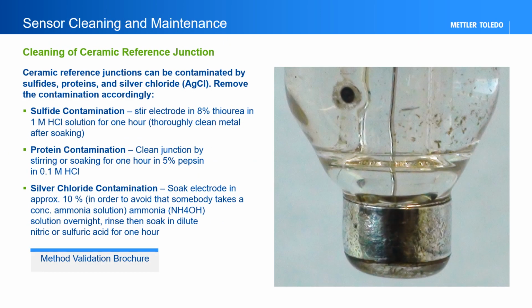A ceramic reference junction can be contaminated over time with sulfides, proteins, or silver chloride precipitate. This contamination can block the flow of the reference electrolyte and must be removed. Pictured here is a silver ring electrode with a ceramic reference junction contaminated with sulfide.